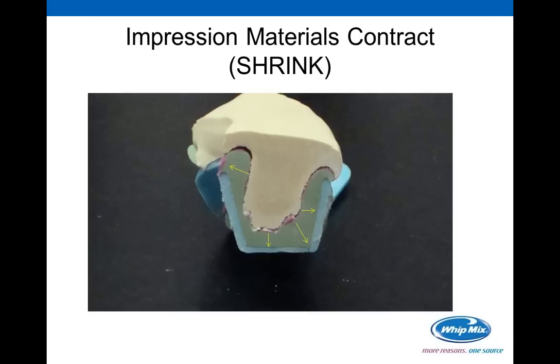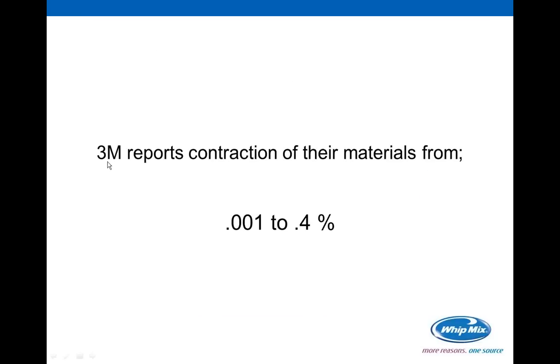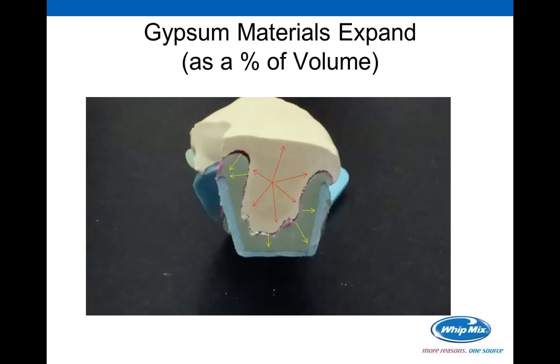Now, let's think through that statement just a bit. We can look at the next two slides. Let me tell you first that 3M, which is a major player here, reports the contraction of their impression materials anywhere from 0.001%, which is very tiny, to 0.4%, just depending upon the material. And that's a good linear change when you're thinking about impression material. Now let's take a look at this slide. If gypsum materials expand and impression materials contract, what's really happening? If you look at the yellow arrows here, you'll see where the impression material is going as it contracts. So the die space is actually becoming larger as the impression material contracts. So why would you put a large expansion die stone in that space, which will actually make that die even larger?